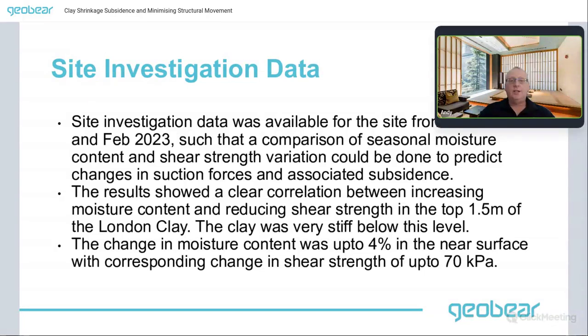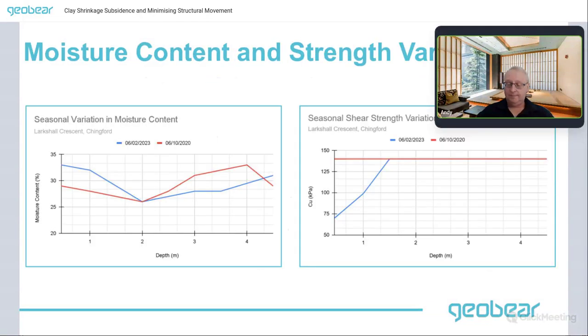The change in moisture content was up to 4% in the near surface, with a corresponding change in shear strength of up to 70 kPa. So changing moisture content changes the soil stiffness. And this is another way of identifying desiccation: to look for areas where the soil strength is higher than the average or against a control borehole. It's another way of indicating desiccation, not only from the liquid limits and the moisture contents, but also the shear strength is a bit of a giveaway.